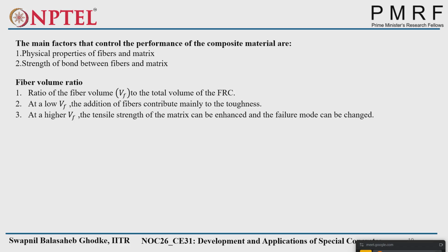Can anyone tell me what the toughness is? Actually, what does it indicate in the load deflection graph? Anyone? Right. It is represented as the area under the load deflection curve. But up to what point, that we'll see. We cannot get the whole area. We'll calculate up to a certain displacement or certain deformation point. Up to that point only we measure the area under the load deflection curve, and that is what we call the toughness of that particular concrete matrix.